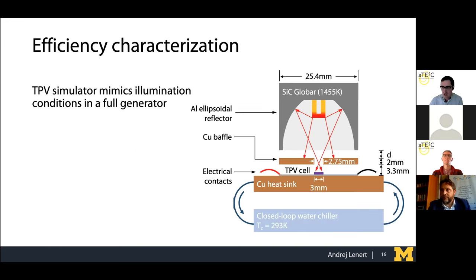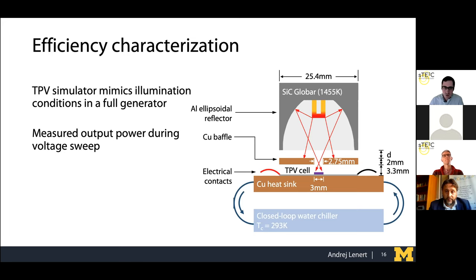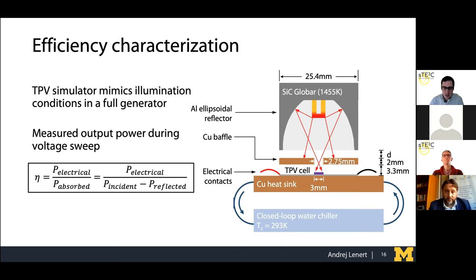So we went ahead and characterized the efficiency, and I'm not going to spend too much time on how we do this, but if you're in the field, there are some nuances as to how you characterize the efficiency of such small cells. We made them on a 3-millimeter scale. And so we decided to go with what we call a TPV simulator that mimics illumination conditions in an actual generator. We measure output power and we calculate how much is absorbed by the cell based on our FTIR measurements. And then we produce a power conversion efficiency that is a ratio of electrical power output versus what would be absorbed by that cell.